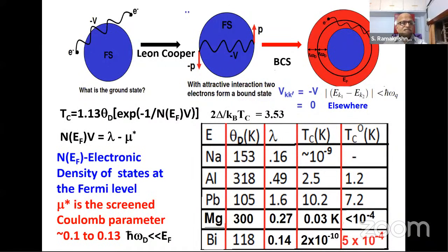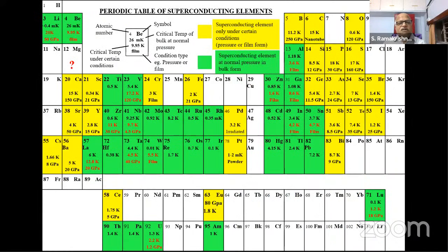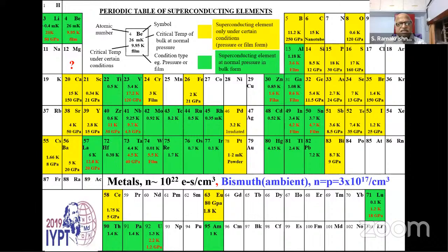I told you, right? In bismuth, you have a lattice energy which is comparable to the Fermi energy. So the adiabatic approximation that the ions will relax and then the electrons come and get attracted, that won't happen. That will not happen. So the basic assumption of the BCS is gone. So we come back to the bismuth again. As I told you, bismuth is 5 orders of magnitude less in carrier concentration compared to the normal metals.